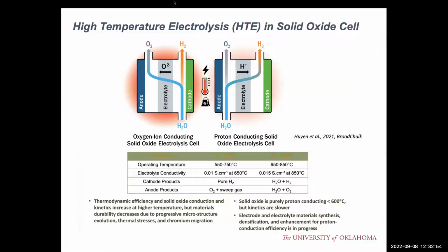So if we can reduce the operating temperature to be a little cooler, right, it can reduce this kind of stress in the system. So for the proton conducting SOC, because the proton is smaller, the transport of the proton through the electrolyte is easier, which can reduce the activation energy for the proton transport. As a result of that, the proton conducting SOC can be operated at a lower temperature, which can relieve those kinds of issues caused by high temperature operations. Definitely, we have also some other advantages. For example, the proton conducting SOC can produce clean and dry hydrogen, without any separation between the hydrogen and the steam.